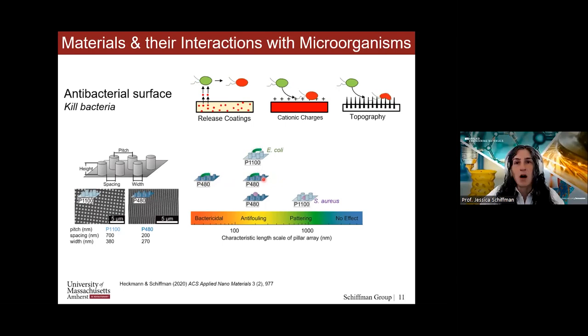Okay. But what we also see is when we look at the larger pillars that are about the same size as the E. coli, they don't kill them. Maybe the bacteria are starting to fall within that spacing of the pillar. And these are all for the E. coli. Okay. Down below, I'm showing this MRSA, this Staph aureus. This causes those hospital-acquired infections, and they're round, they're smaller. And this smaller bacteria with this really tight membrane, they actually just sit on top of the smaller pillar arrays. And as shown previously by some colleagues in the Eisenberg group, when we have this larger pillar array, the MRSA just arrange within it in a very ordered fashion. And so this is all to say that, of course, not all bacteria are killed by the same pattern. We really need to engineer the size of our pattern to be appropriate to the bacteria.